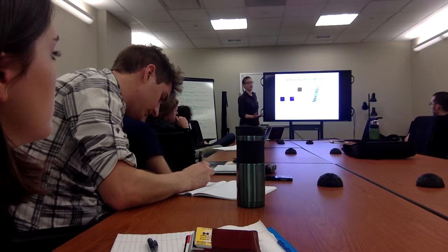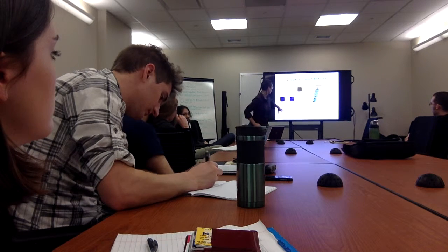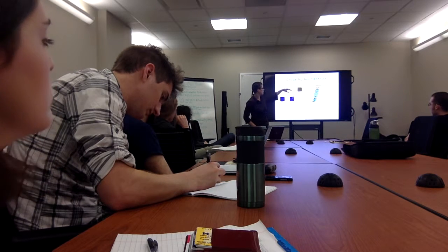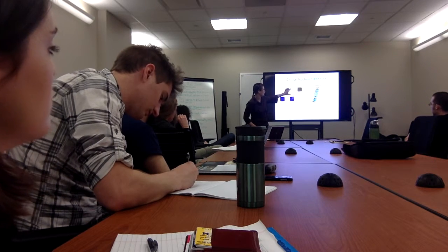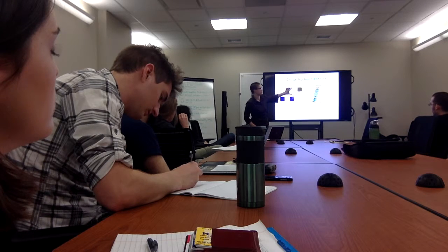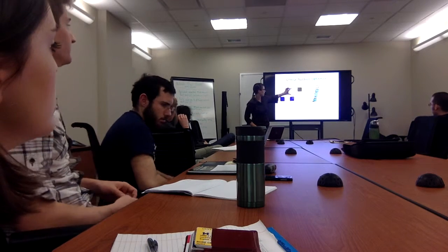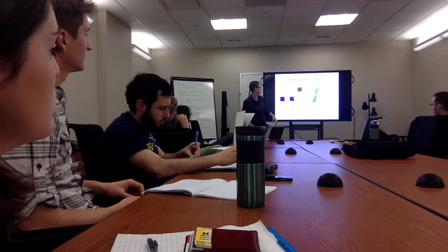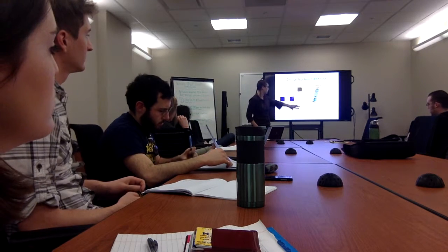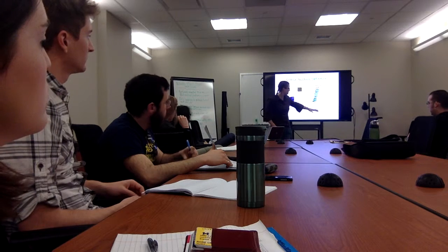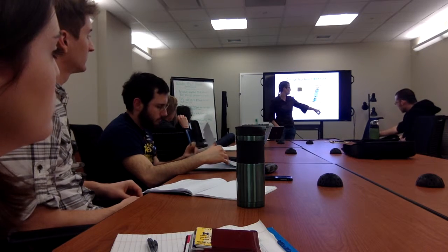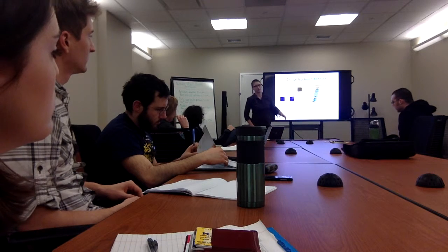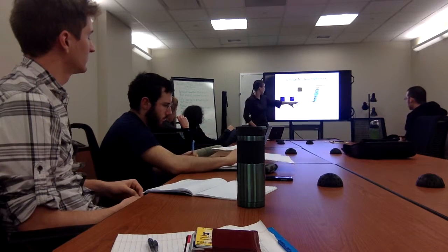When you go into reading the papers, the critical nucleus, as defined based on classical nucleation theory, is this very clear-cut size where there's a peak when you balance the surface tension to the volume, and you can define it very clearly. In practice, the critical nucleus is the nucleus where the probability of crystallizing is 50%. So in practice, you would go the other direction.